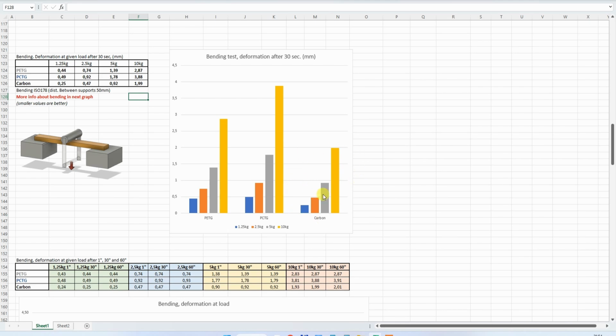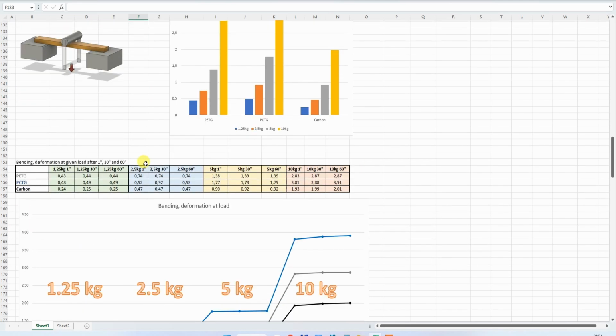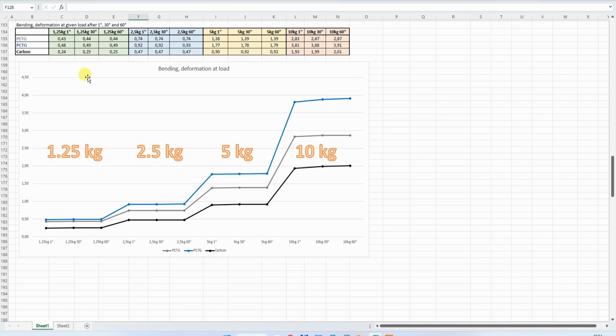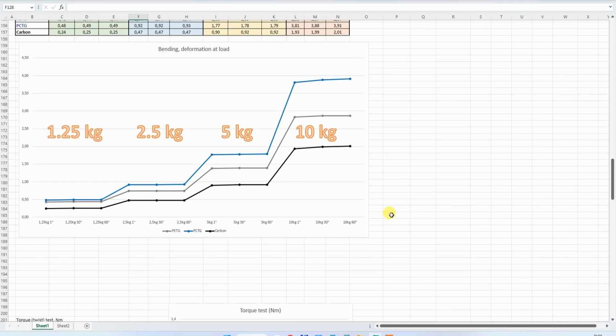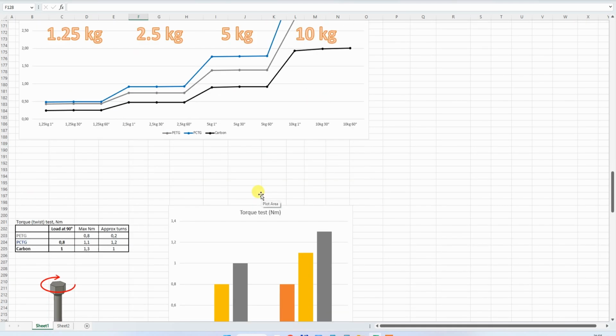The carbon version was the best in this test. And if we analyze this table, where we have the deformation after 1, 30 and 60 seconds on this given load, good values are when we see horizontal lines. We can see on this graph that it is a little bit at an angle. This means we have this creeping during this 1 minute of the testing. So in this test, again, the carbon filament was the best.